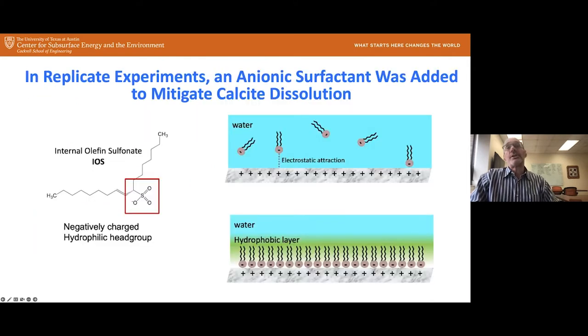Also, we were interested in seeing if we could use an additive, in this case an anionic surfactant, to mitigate this calcite dissolution. Here we use a common surfactant used in the oil field, internal olefin sulfonate, or IOS. It has a sulfonate group at the end, which is negatively charged and hydrophilic. The idea is that the calcite is positively charged under the pH ranges of interest in our study. These sulfonate groups are attracted to the surface, so we get a layer of IOS on the surface, or maybe even a bilayer if we have enough IOS, with another layer oriented the opposite way, so we get hydrophobic in the middle and a negatively charged group heading out into the water.